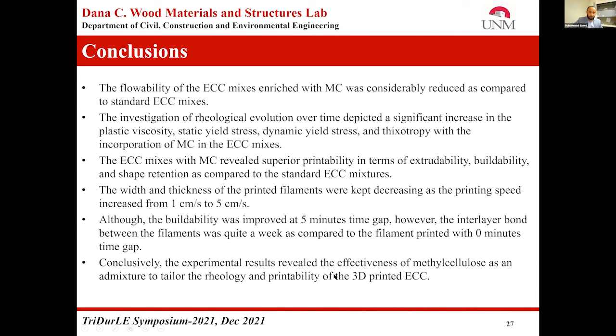In the end, we can conclude that methyl cellulose could be an effective admixture to tailor the rheology and to modify the printability of 3D printed ECC mixes.